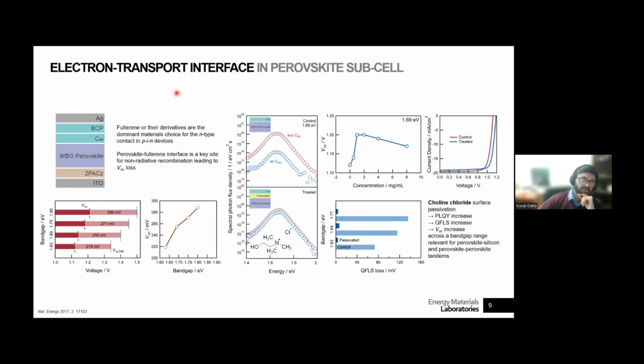The next thing we looked at was the interface between the perovskite and the electron transport layer, so the perovskite and the C60. And the one thing that struck us was that if you take a perovskite with a certain band gap, let's say 1.63 eV, and then you widen the band gap to 1.80 eV, what you see is that the voltage, which is this dark part, keeps on going up as it should, but it doesn't go up by as much as it should, right? And that's because the VOC loss compared to the radiative limit also keeps on rising. So that's here, the loss, sorry, this should be loss, as a function of the band gap that keeps on rising. So that is a strong limitation to the performance of these tandem devices.